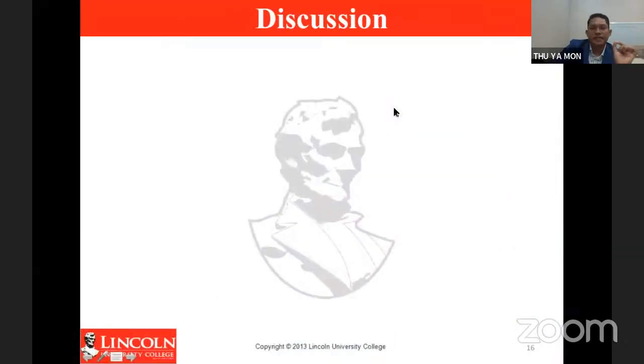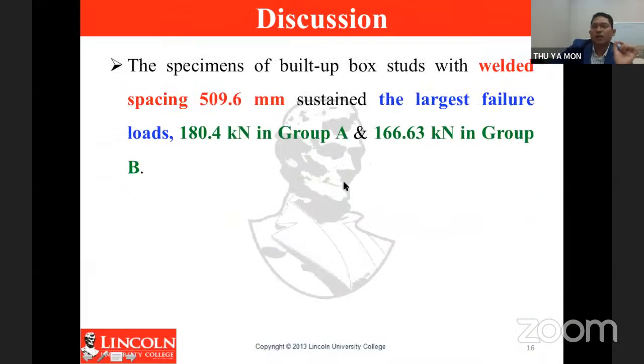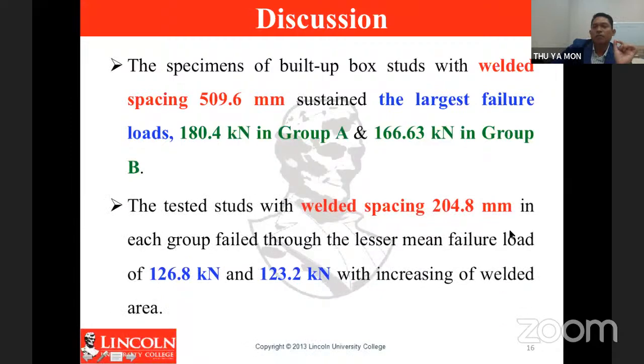So for section 4, discussion. Based on my experiment, the weld spacing of 509.6 millimeter sustained the largest failure load of 180.4 kilonewtons in group A and 166.63 kilonewtons in group B. Once the weld spacing decreased from 509.6 millimeter to 204.8 millimeter, the failure load changed, ranging from 180.4 kilonewtons to 126.8 kilonewtons in group A and 166.63 kilonewtons to 123.2 kilonewtons in group B. This showed that decreasing the weld spacing reduced the failure load.